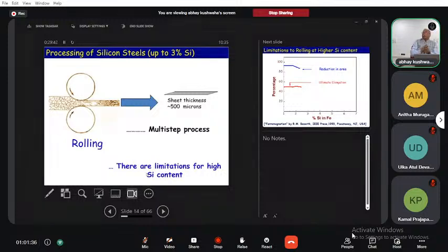And you see how you process this material. So you can understand now the 6.5% silicon steel is a better material because its losses are less, and also the resistance is high. When we process this material, we prepare it in the same way we prepare steel. That is, it has to be melted, it has to be cast, and then it has to go through a rolling process. Rolling uses two big rollers, just like you have seen sugarcane juice is prepared when the sugar cane is pushed in the roller. Here also the steel in its hot condition is passed through the rollers and it reduces the thickness. So pass by pass, we reduce the thickness.